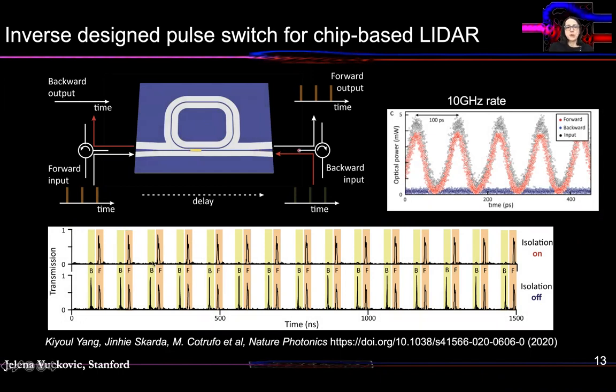You see only propagation of the forward pulses in the orange slots, but you don't see propagation of the backward pulses. If you are outside of the dynamic range of non-reciprocal propagation, then you are not blocking backward pulses. So this non-reciprocal behavior can also be performed at high speed. We demonstrated that we could do this isolation at even 10 gigahertz rate, as shown here, where you are transmitting forward signal but blocking backward signal.